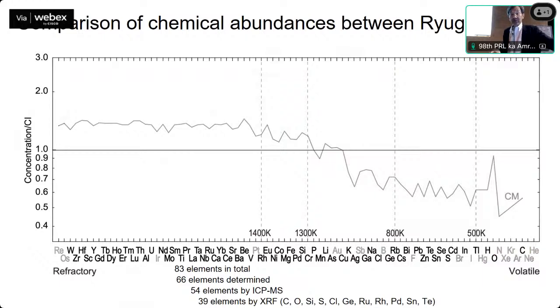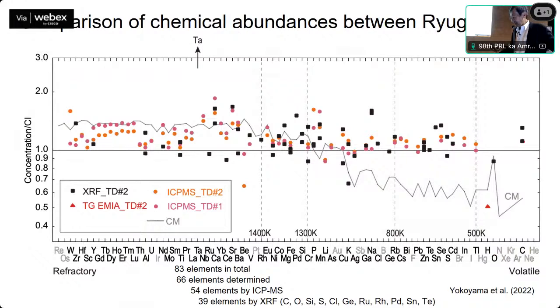Why is the volatile element concentration important? Because CI chondrite should plot on this line, value 1.0, since the concentration is normalized to CI chondrite. But the volatile elements of other meteorites are depleted relative to CI chondrite. So determination of these elements is very important. And this is the result. You see the volatile elements plotted here. So no depletion of volatile elements. This strongly supports that Ryugu is similar to CI meteorite.